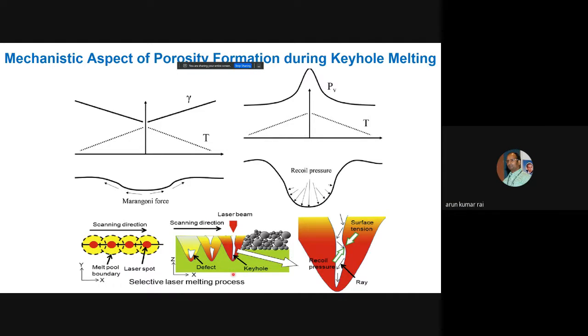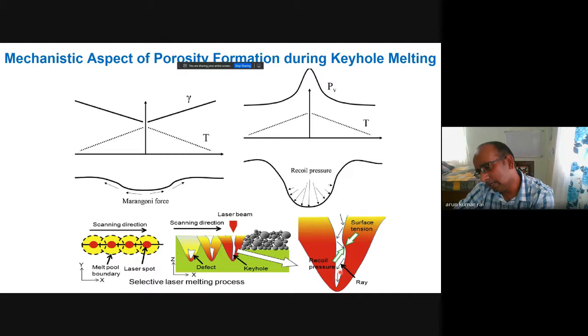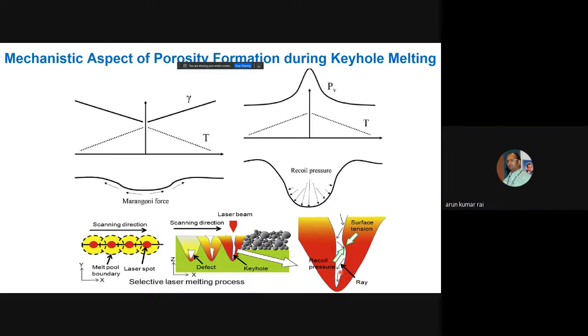So if you have excess melting, then that can lead to formation of a keyhole kind of defect. That is what I have shown you. So these are the two parameters which play a role in the formation. So what will happen when you are going deeper and deeper? This material will not be able to fill over here due to the Marangoni effect. Okay. However, this recoil pressure will keep on penetrating down, but due to the Marangoni effect, material will flow outward, and this area will be left vacant if the gas is there, and that leads to formation of pores.